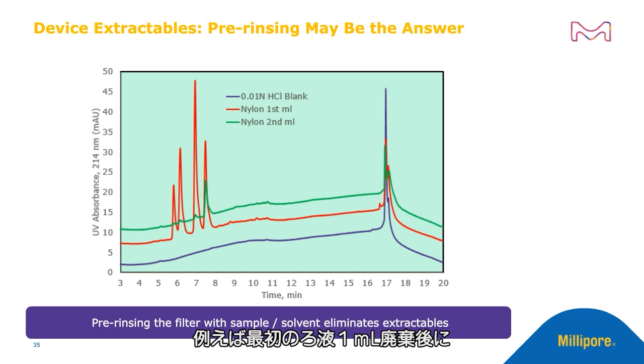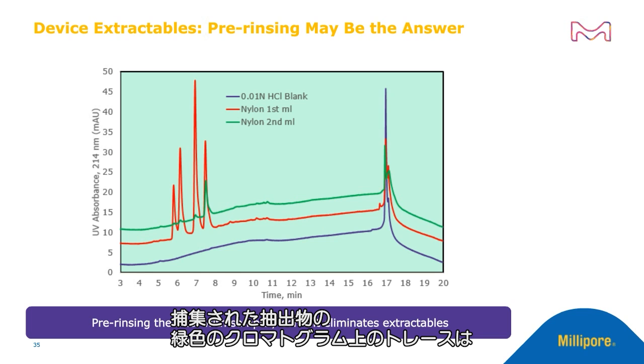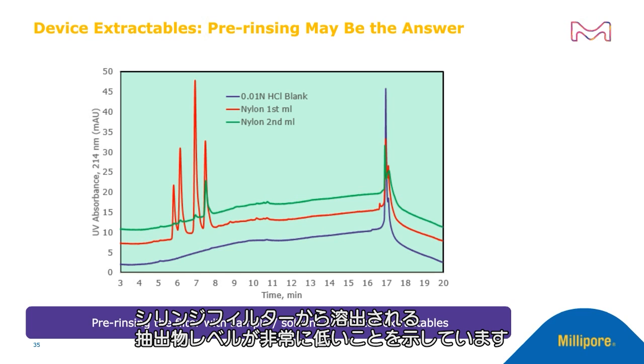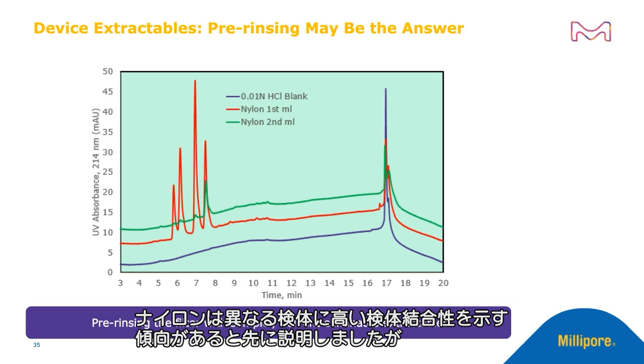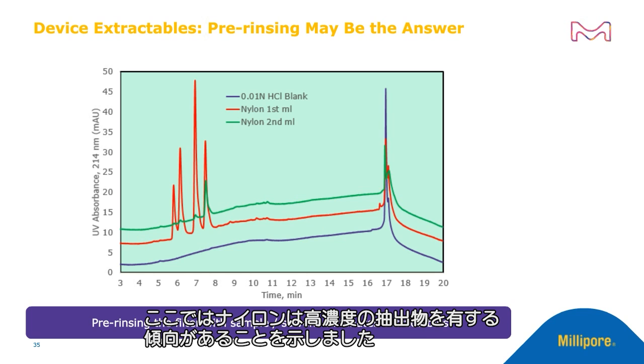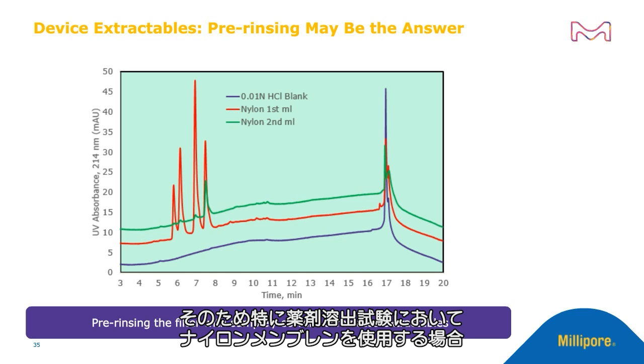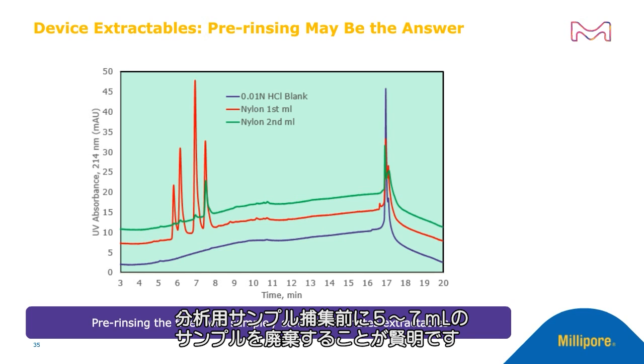For example, if you can see the green chromatographic trace, which shows the extract that is collected after discarding the first ml of filtrate, it shows a much lower level of extractables eluting out from the syringe filter. We saw earlier that nylon also tends to show a higher level of analyte binding for different analytes. And now here we are showing that nylon also tends to have a higher level of extractables. Because of that, especially when using nylon membrane during drug dissolution testing, it is prudent to discard 5 to 7 ml of sample before collecting sample for analysis.